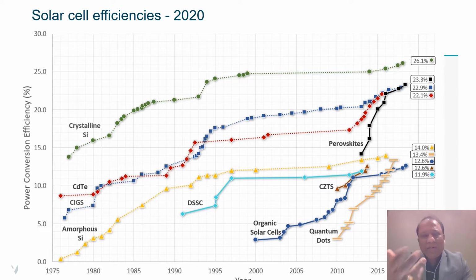Recently, you can have a look, this is from 2020, so there are some changes now. But if you look at this, as far as silicon is concerned, it took nearly 30 years to reach this level, 26.1% efficiency. And look at CIGS, even that took a lot of time. Look at quantum dots and dye-sensitized solar cells, from 1996 to now, it's still around 12% efficiency. Nothing has changed. But look at perovskites, with black marks here.